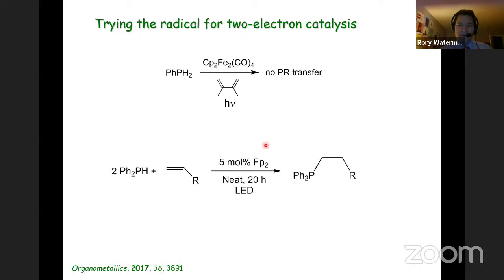So what we have observed, and simply for the length of time available, we found that Fp dimer actually is activated in solution, and it appears through a cooperative process. P-H activates at the phosphide, so presumably we're generating an equivalent of the iron phosphido and the iron hydride. The Fp hydride is known to decompose back to Fp dimer, so that makes a clean loop to continue to reactivate catalyst, and presumably then the Fp phosphide can undergo an insertion reaction and provide the hydrophosphonation product. And so that reactivity was interesting. The photolysis is important for the P-H activation step, not for the overall turnover. So this is photoactivated chemistry, not photocatalytic.